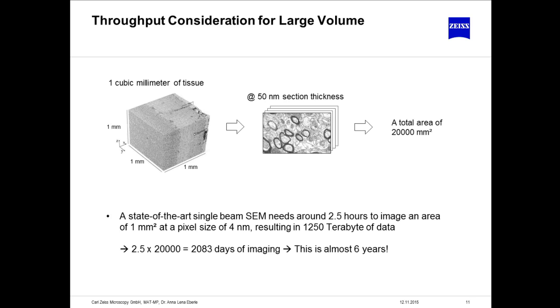A state-of-the-art single-beam SEM that is well-equipped needs, ballpark figure, around 2.5 hours to image an area of a square millimeter with a pixel size of 4 nanometers, which is the resolution that is sufficient and needed to get images that are well resolved enough to make a circuit reconstruction in the end. Data-wise, this will give 1,250 terabytes of data, which is 1.25 petabytes, basically. So now, beyond the terabyte, we can also use the petabyte term.